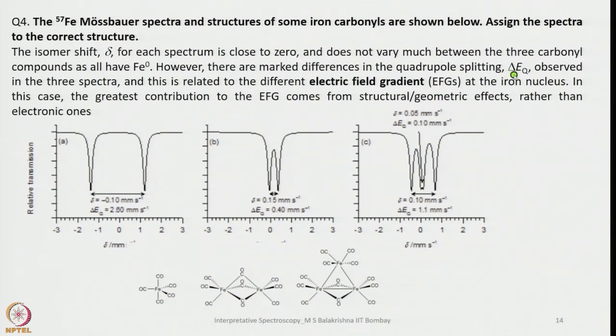Quadrupole splitting is delta EQ, and the isomer shift is small delta. This is observed in the three spectra, and it is related to the different electric field gradient at the iron nucleus. In this case, the greatest contribution to the EFG comes from structural and geometrical effects rather than electronic ones.